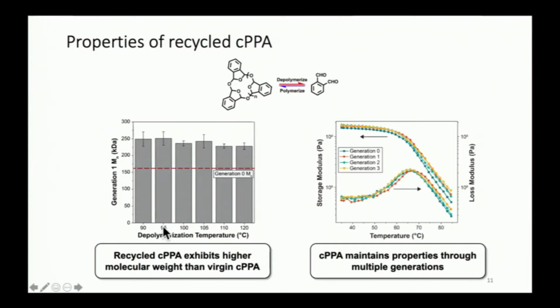For example, regardless of what temperature we do it over the typical range we like to depolymerize, we can still take that monomer and get high molecular weight polymer out of that, well above 100,000 molecular weight, following that initial cycling event. And then the plot on the right is some dynamic mechanical analysis for a series of generations having gone through this loop, and the material's properties are maintained in this sequence of cycling.